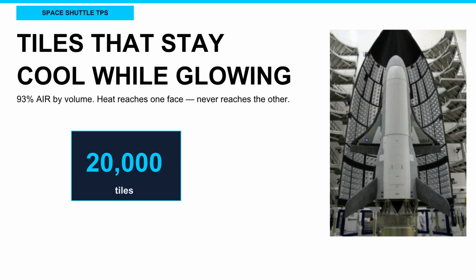Density, about 144 kilograms per cubic meter. For comparison, water is 1,000 kilograms per cubic meter. The silica is an extremely poor thermal conductor. Heat absorbed on the outer surface travels slowly through the tile. By the time re-entry is over, the heat has not yet reached the bond with the aluminum frame. The tiles can be held by hand on one side while the other side glows at 1260 degrees Celsius. That demonstration was used in shuttle-era training.